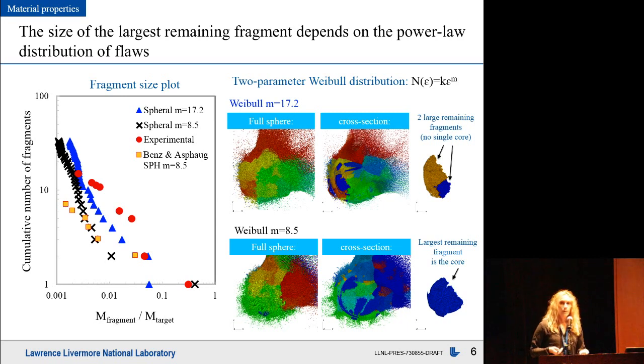So Benz and Asphaug did this for their own SPH code, where they found the exponent M parameter equal to 8.5 to best match the experimental results for larger fragment masses, but not so much for the smaller fragment masses, where the experimental results are shown in these red circles and Benz and Asphaug are these yellow squares.